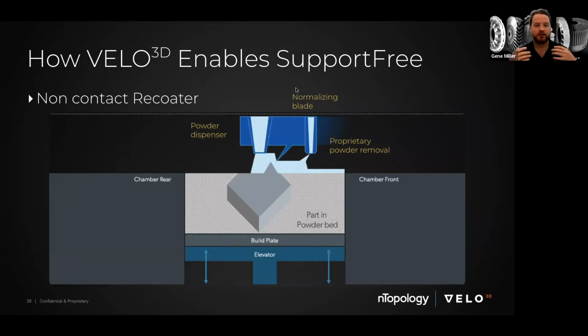So on a high level, here's how support free is enabled by the non-contact recoater. We have a powder dispenser that snows down gently a thick layer of powder over the substrate of the powder bed. Behind that is a normalizing blade that flattens and normalizes that surface after it is dispensed. And behind that, that's where the magic happens. That's our proprietary powder removal tool that comes in behind the normalizing blade and removes all but 50 microns of powder. So the net is the same. We still have a 50 micron thick powder bed, each layer, but we never actually come in contact with the part. We don't have to worry about movement or interference with the recoater.